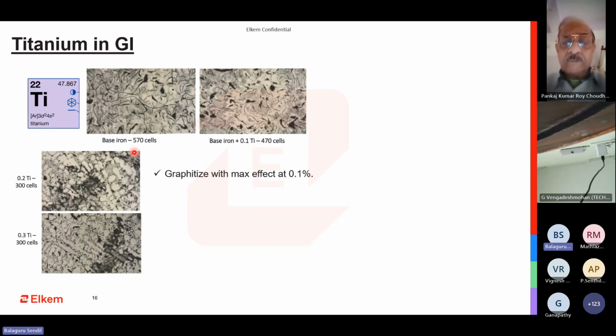When you are using a higher rate of scrap in your charge, and that particular scrap has high titanium that you are getting automatically, then you should control the titanium from all other raw materials that you are having. The titanium can come from your recarburizers, from your pig iron, from your returns buildup, from your inoculant, from your poorly made magnesium. All these things are going to give you titanium in it. So how are you going to control it?